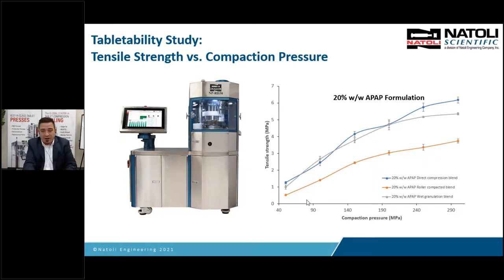It only required about 80 megapascals of compaction pressure. That's a very low pressure. If all you need is 20% drug load for APAP, we could do this easily. A very low compaction pressure, you're not going to wear out your tools quickly. Your tablet press is going to, the force is going to be very low, so you won't wear out your press quickly.